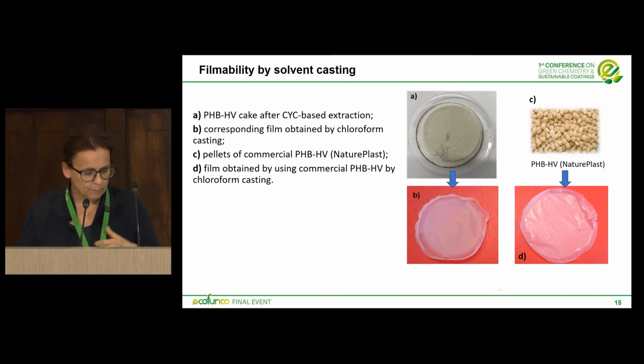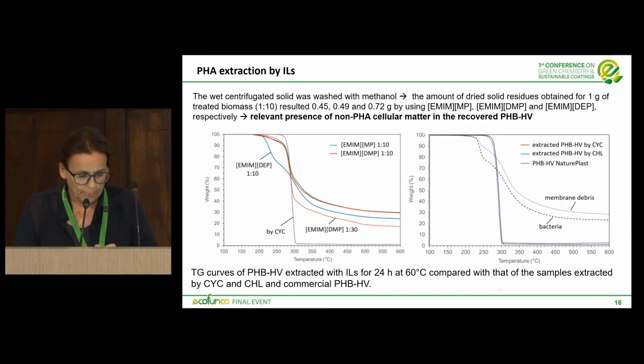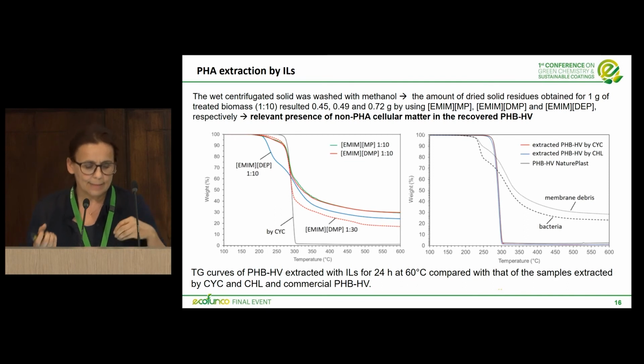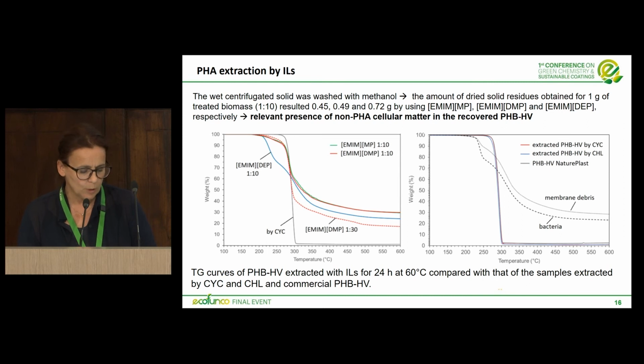Similar. The films obtained from the commercial PHB-V by NaturePlast and the PHB extracted by cyclohexanone. So, about the results obtained by PHA extraction by ionic liquids. In this case, the results were not so good as those obtained by cyclohexanone because the dried solid fractions obtained using the ratio ionic liquid to biomass of 10 and also 30 to 1 contain a relevant presence of non-PHA cellular matter.